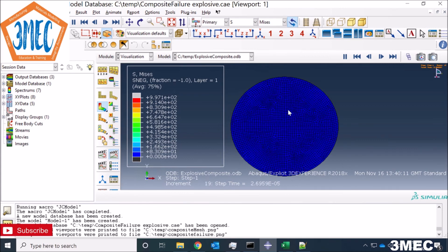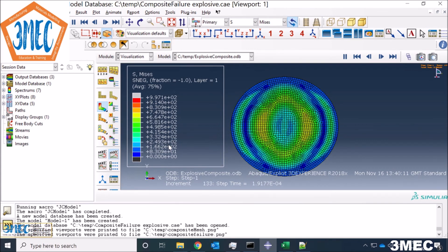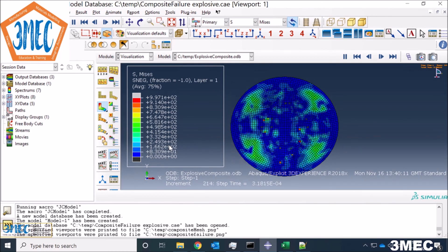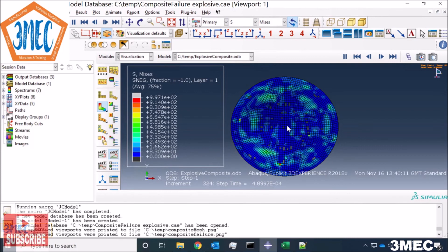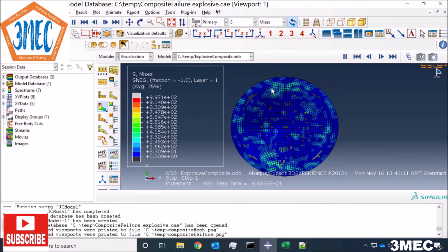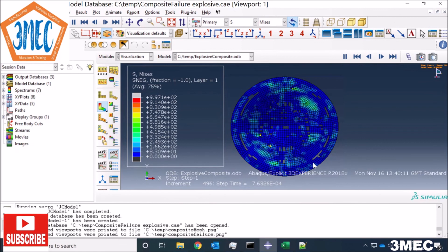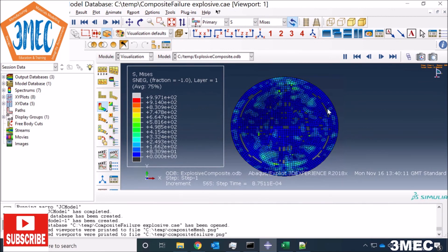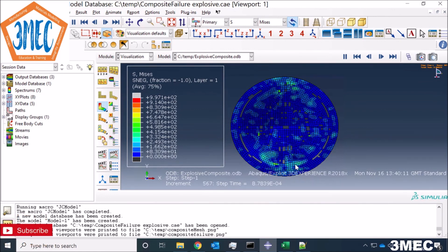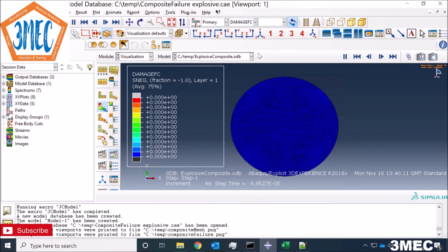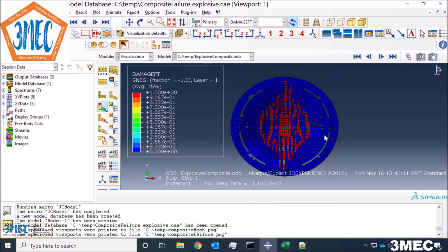It's better visible when you see from the front. You see how the stresses are generated because of the pressure wave or explosion, and then you see the failure starting in this area first. Then also mainly it failed near the boundary conditions or the place where it's being fixed because of the stress concentrations. You can also see damage due to what, so you can play around with that. If you look at this, you see damage due to the fiber in compression is in these areas. Damage in the tension is this area because this is highly under tension loading and some areas are already failed because of that criteria. You can play around with that and see how it's doing in this way.